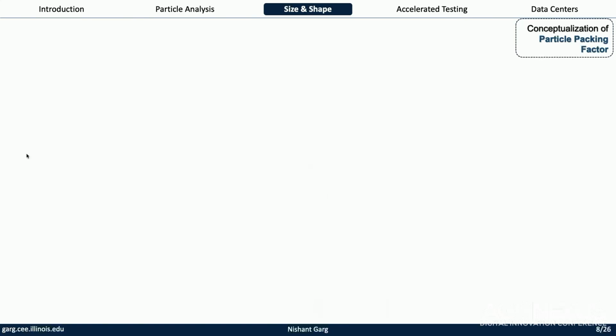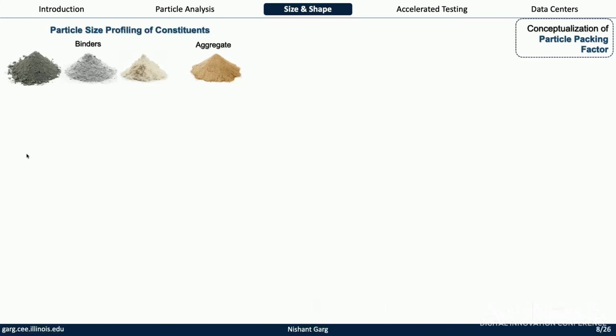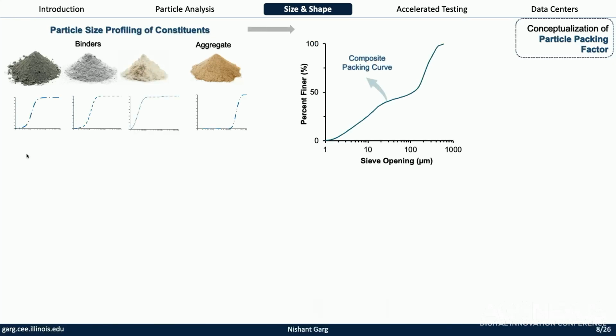So we came up with this metric called the particle packing factor. And the way we went about this is very simple. We said, okay, let's take all the ingredients in concrete, starting from aggregate to all the binders, right? Cement, fly ash, slag. Let's measure their particle size distributions. Let's look at the theoretical packing curve according to the Andreasen and Andersen model, which says if you have particles in that packing curve, that's the best packing.